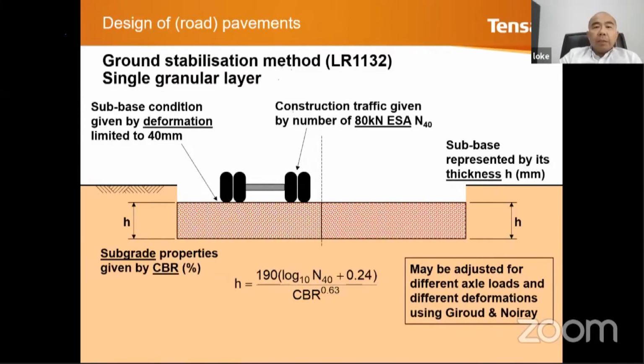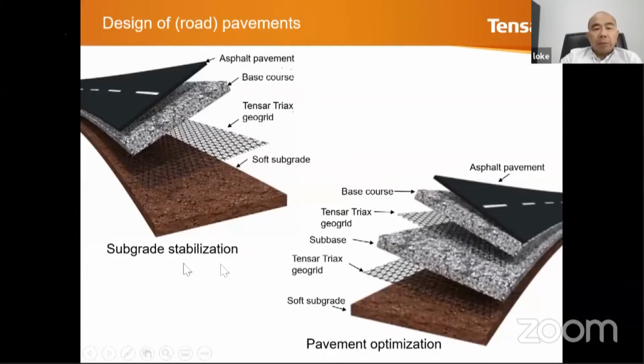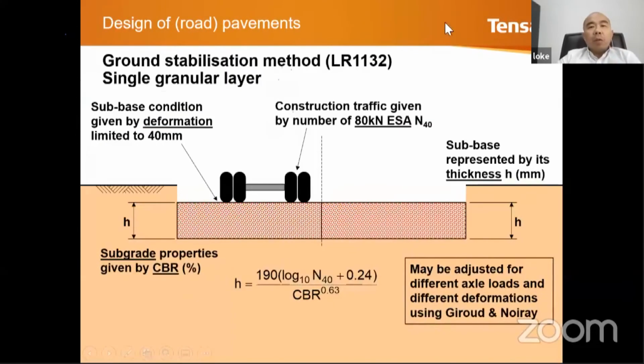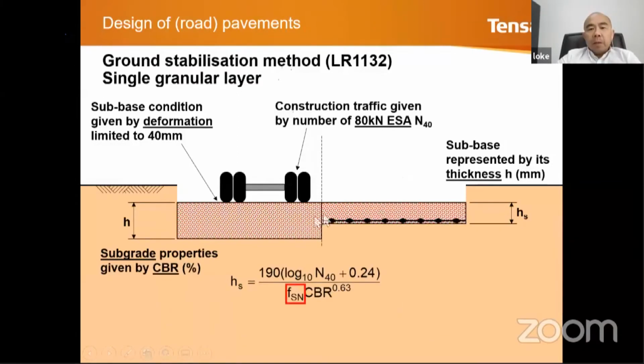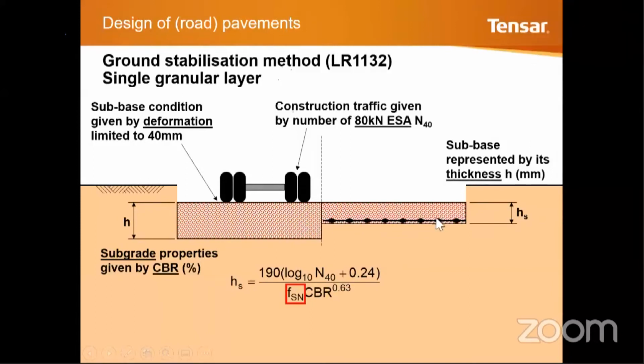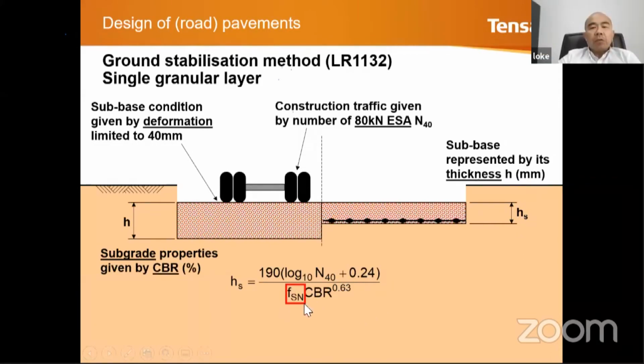So if we look at the first method, which is called the ground stabilization method or subgrade stabilization method, we use the method called TRL LR1132. So you can see this is your vehicle loading. This is the equation. You have the H, and we are using ESAL, equivalent standard axle loading, which is 80 kilonewton. And without geogrid, you can see the thickness. By having a layer of geogrid, you can see the thickness is significantly reduced. Okay, so what we do is we add in this structural number, the factor for structural number, modification of the structural number.